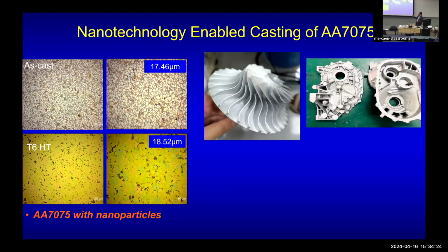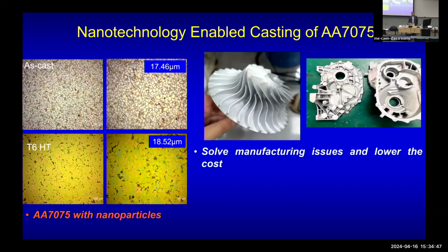But right now you can see we can cast them directly, right? This shape traditionally needs 5-axis CNC milling to make. But right now, in one cast, we can get the geometry. And also because of nanoparticles, we can get very small grain size with slow cooling. And even after T6, the grain size is still very small, right? So in this way, for the first time, we can cast aerospace alloys, right? Solving the manufacturing issue, lowering the cost, no hot cracking, and easy to cast complex shapes.